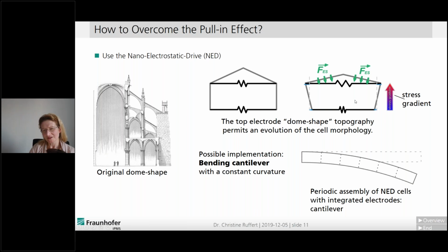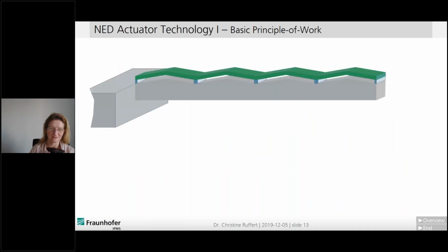Imagine you take a couple of such dome cells and put them in a row, as indicated at the bottom. When you apply a voltage, the upper roof will bend down and the side walls will tilt. What will happen? The cantilever will bend. This is what we make use of in our NED actuator systems, and I will show you in an animation. We have an all-silicon system, apart from the spacer, which is made of alumina in this case to insulate the upper from the bottom electrode. In first systems we also used titanium aluminide, but nowadays it's a full silicon system.